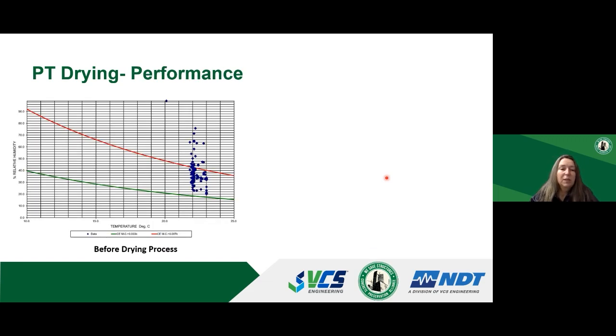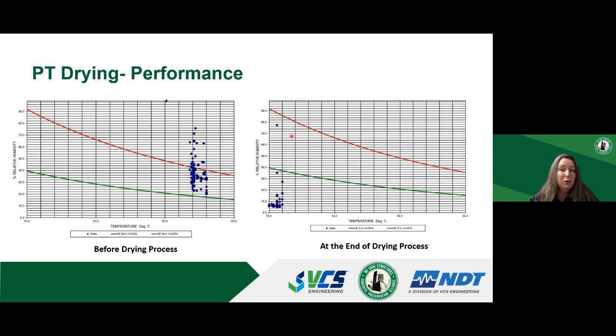This plot shows the relative humidity and the temperature of the tendons at the very beginning of the drying. Again, as you can see, everything is above the green threshold line, so it's a high risk for corrosion. There is one tendon that is actually at 100% relative humidity, and when we drilled that one, water came out of it. The plot on the right shows the relative humidity of the tendons at the end of the drying process. All the tendons except for one were below the green threshold line, so they're in the dry condition. At this point, the drying for these tendons was terminated, and there was one still remaining in the moist condition, so drying for this tendon continued.